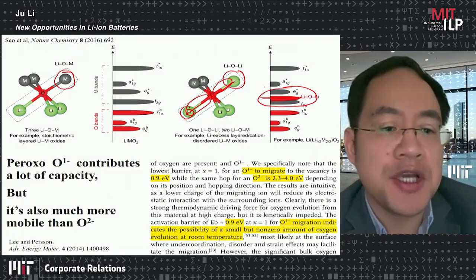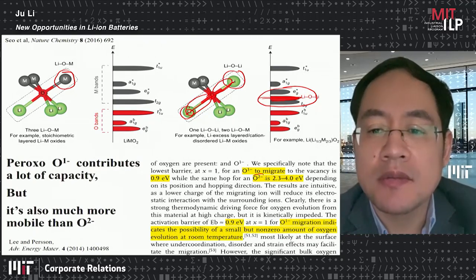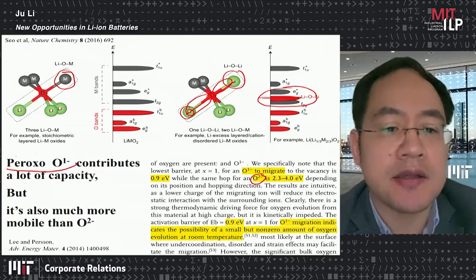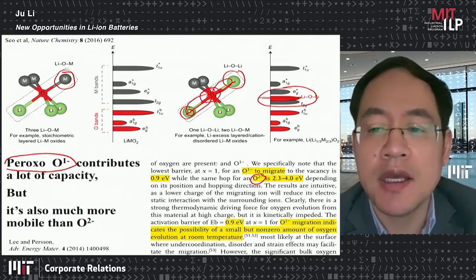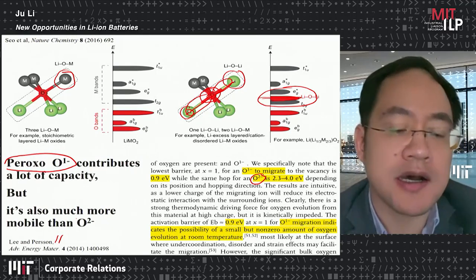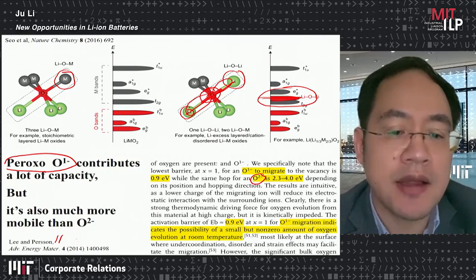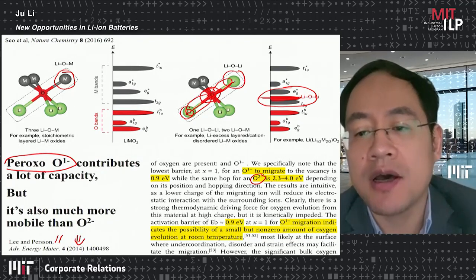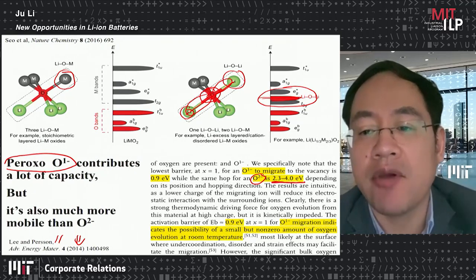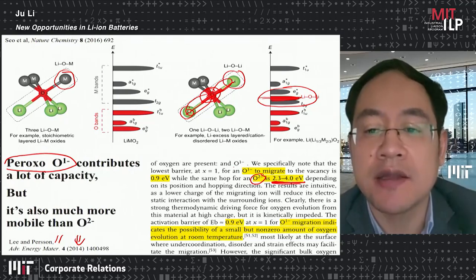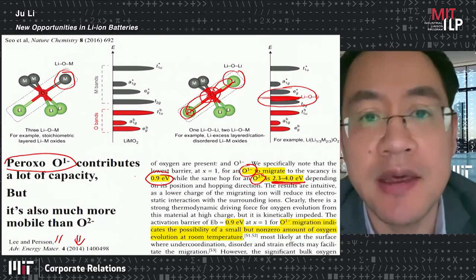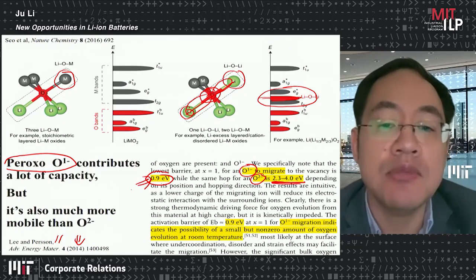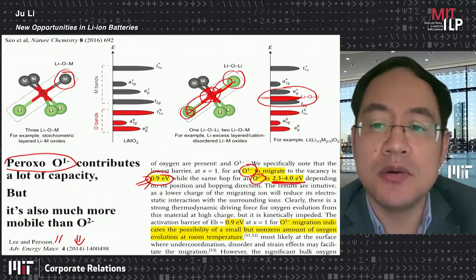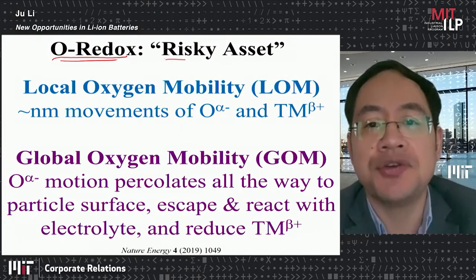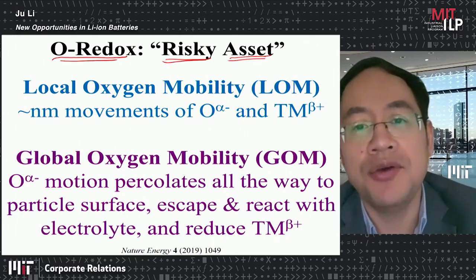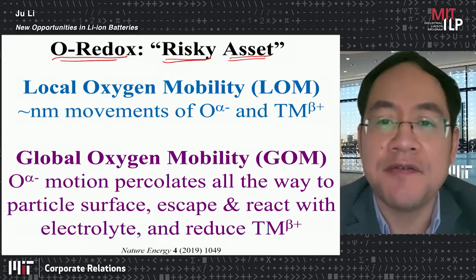But there is a catch, which is that anytime you convert your typical oxide to peroxide, the migration barrier for this oxygen basically reduces. So this is work from Professor Persson in 2014, DFT modeling that showed that when you go from oxide, which has a migration barrier of 2.3 to 4.0 eV, to peroxide, the migration barrier drops to 0.9 eV. And that means you can basically move at room temperature. And so oxygen redox, therefore, is intrinsically risky. It is an asset that you can use, but it comes with the following problems.